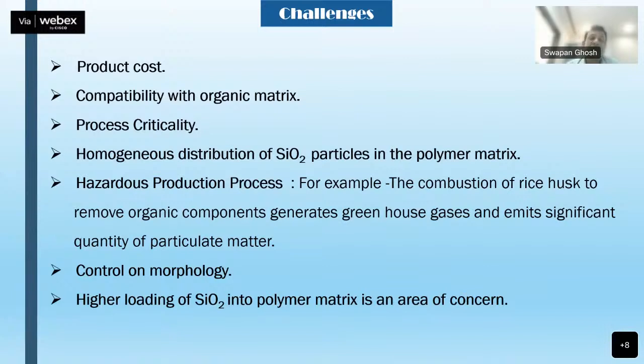Then process criticality. Process criticality is very important. For example, in the slide that I was explaining, if I have 4 ingredients and one of the ingredients is not compatible, then at one point it will happen that the complete batch will gel. To give you an example, only to incorporate 0.6% of silica in an emulsion polymerization, somebody is using a silane, and if that is not added properly, the whole batch will gel. So the process is very, very critical. Then obviously homogeneous distribution of SiO2 particles is also very critical. Otherwise, you don't get the advantage of this silicon oxide particle.